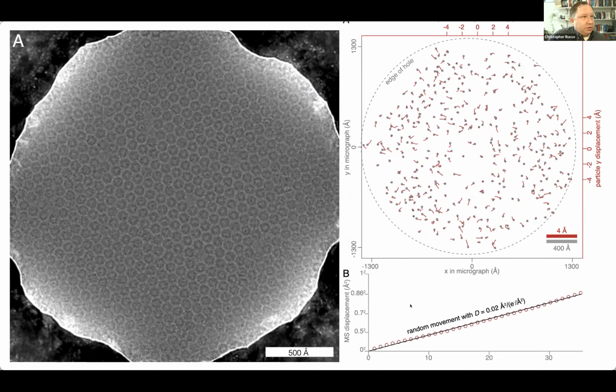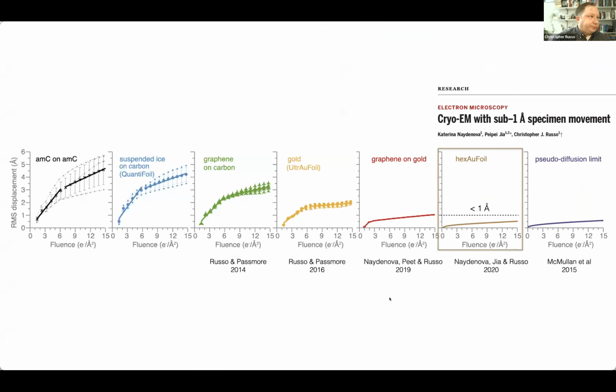So this really shows, first of all, that the movements of these particles are all now uncorrelated. So now it really is not some bending or movement of the ice layer. And it should track beautifully according to how much we think the water molecules are moving themselves and causing this random pseudo diffusion of the particles. So all of this then lined up together. So we were pretty confident that we're on solid ground now.